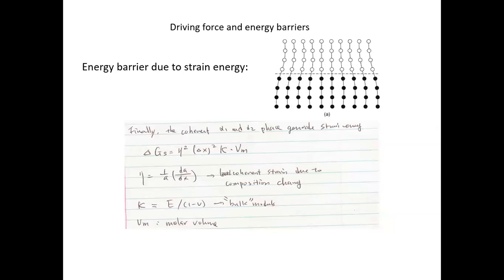Also there's a strain energy to the system. Although they probably have the same crystal structure, because the atoms are of different sizes, there might be a strain energy related to this. The strain energy is proportional to delta X, which is a composition difference, and K is the bulk modulus, Vm is the molar volume for the system, and eta is a strain.